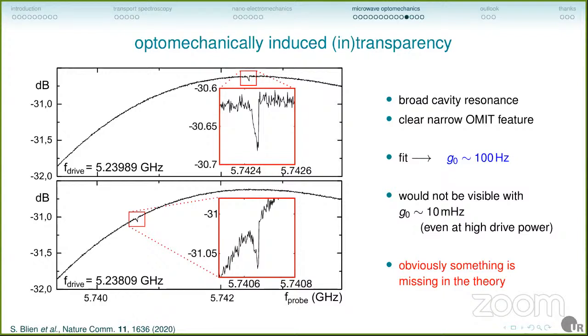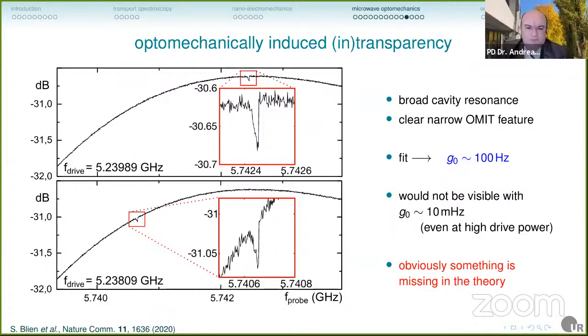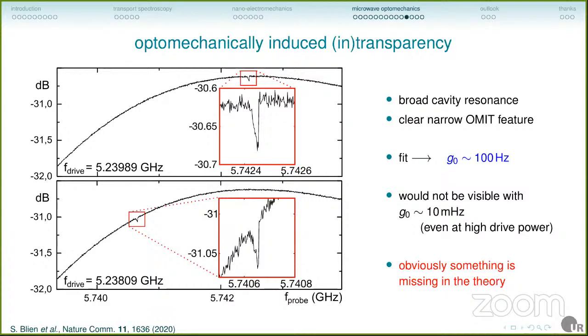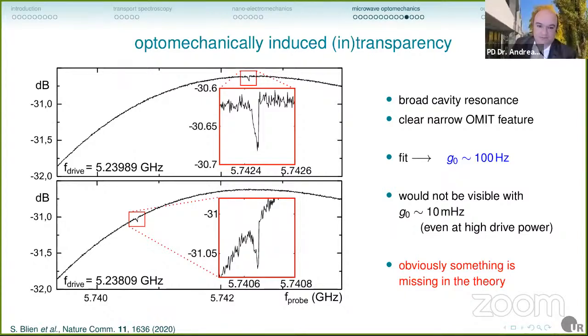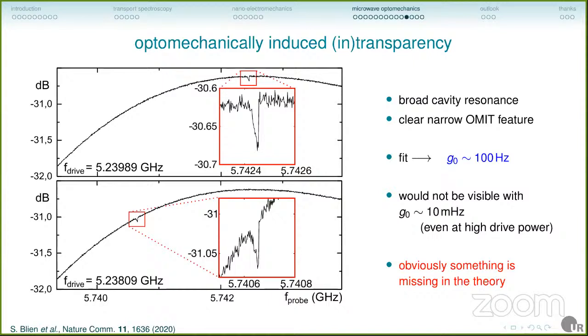But for curiosity, what was your Q factor of the resonator? Because I was not listening to the whole talk. For the mechanical system, I don't know exactly anymore, but maybe somewhere around 20 to 50,000. 20 to 50,000. Okay. And the photonic? Low, 500. That was a fabrication defect. Oh, this can be made much higher, no?